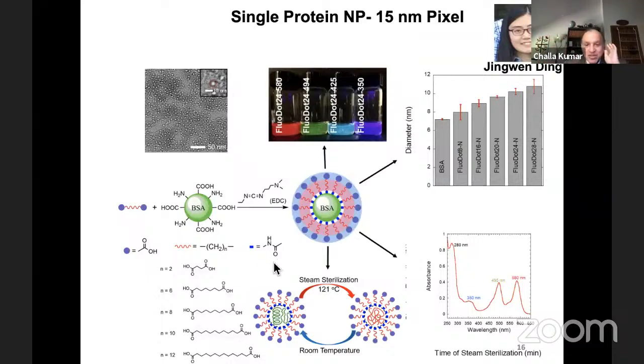And what she found is that when you heat it to this, it undergoes denaturation to some degree. But when you cool it, it completely falls right back to its original state. Maybe we lose 1% or 2% of the protein. And you can do this all day, heat and cool, heat and cool, many, many times. What that means is we have changed the biochemistry of this molecule in a dramatic way. Without this chemical modification, if you heat it, it will aggregate and precipitate out. It's like making an omelet from an egg. You throw the egg onto the pan and it denatures and you get an omelet. The omelet doesn't go back to the egg. But here, the omelet goes back to the egg when you cool it back to room temperature. So this is cool chemistry.